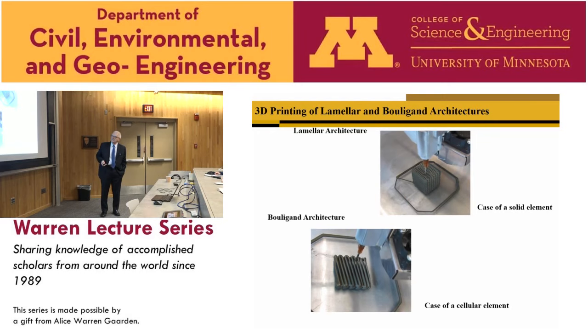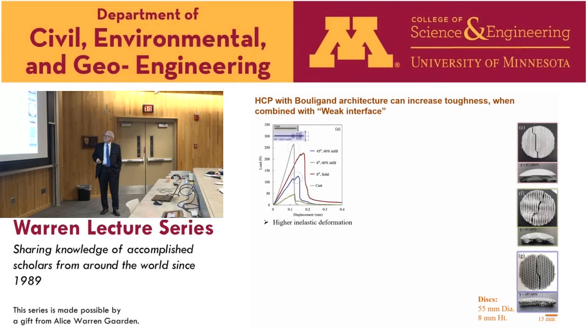and the printer is capable typically of keeping a very good shape. We produced a variety of those elements, beams and cubes, and we tested them, looking at the mode of failure. If you look at the load versus displacement, the gray one here is the cast element, and then you have this Bouligand structure with various degrees of orientations of filaments and various percentages of infilling. Some were essentially solid, some were not so solid.